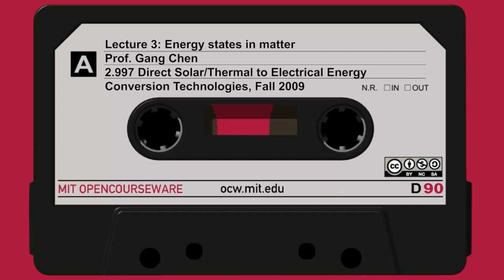And here it looks very similar to a free electron. This is just a second order derivative of the curvature. Now if I treat that just as a mass, an equivalent mass, which I call the effective mass, then it's a free electron. I can then do the rest of my work as a free electron. So it's a mathematical simplification.